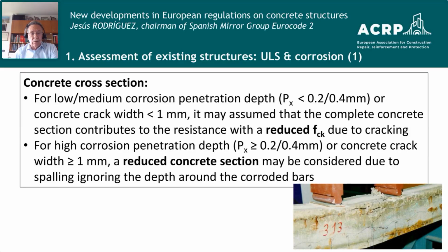In relation with the corrosion, although it is said that there are only general considerations, I would like to highlight that there are some recommendations on how to deal with the reduction of the concrete cross section and the steel cross section. In relation with the concrete cross section, there is a recommendation to consider the complete concrete section, but with a reduced value of the fck when there is not a high level of corrosion. In this case, we can consider all the section, but with a reduced compressive strength of concrete due to the presence of cracks. And when there are high corrosion values or relevant cracks with width higher than 1 millimeter, we need to consider the possibility of the spalling of the concrete and consequently use the reduced concrete section.